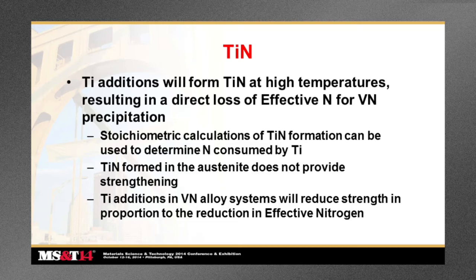We know that titanium nitride can form at a very high temperature. It results in a direct loss of effective nitrogen for vanadium nitride precipitation. And basically you can use a stoichiometric calculation of titanium nitride formation and presume that virtually all of that nitrogen will not be available and will not be part of the effective nitrogen available to the vanadium. The titanium nitride formed in the austenite does not provide strengthening.